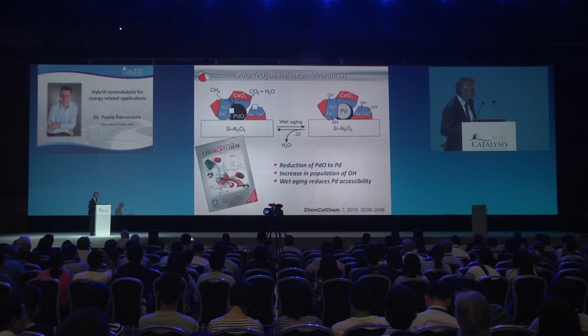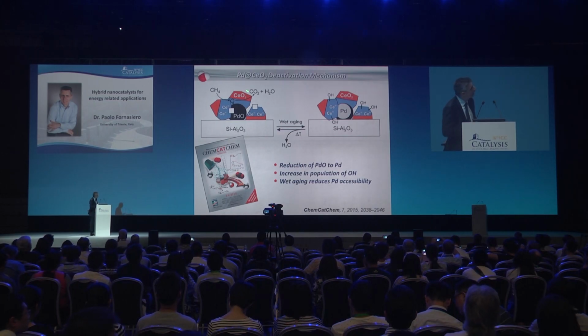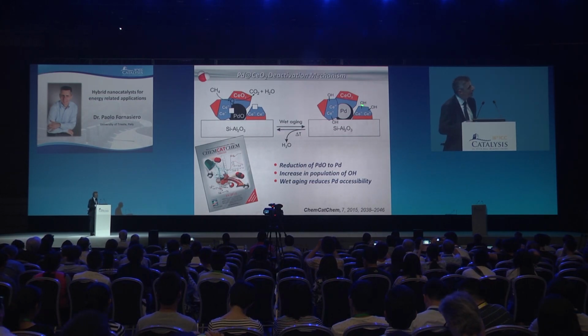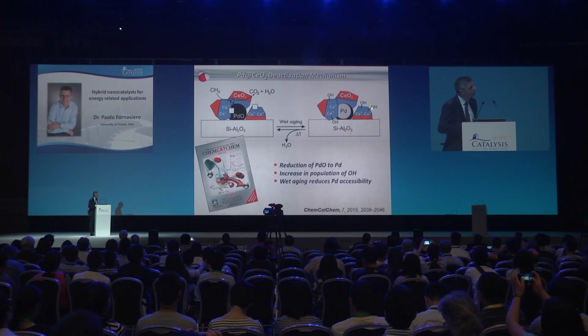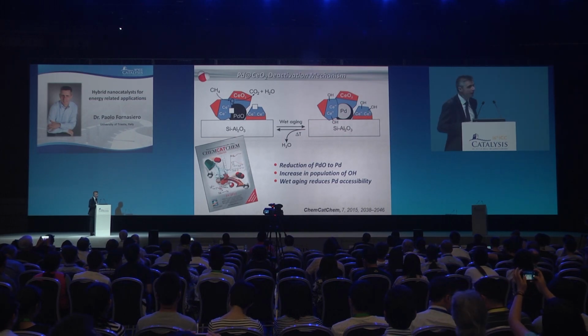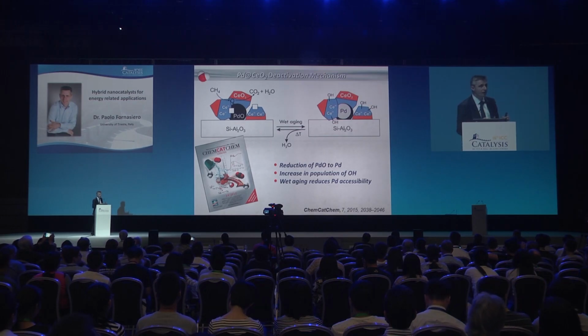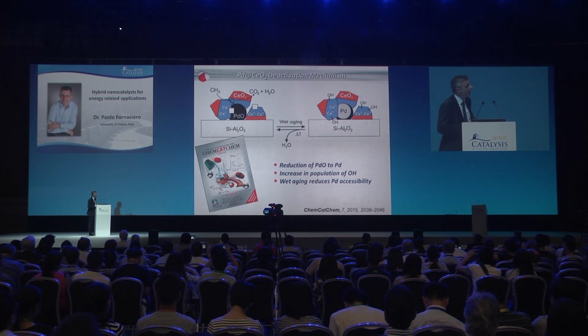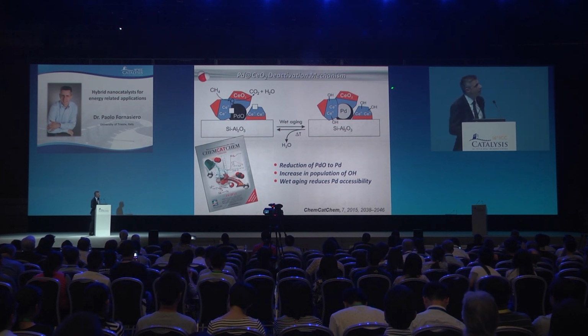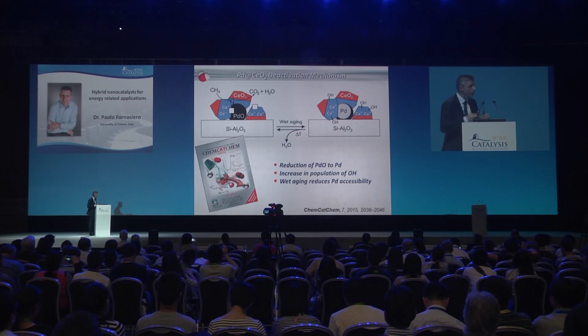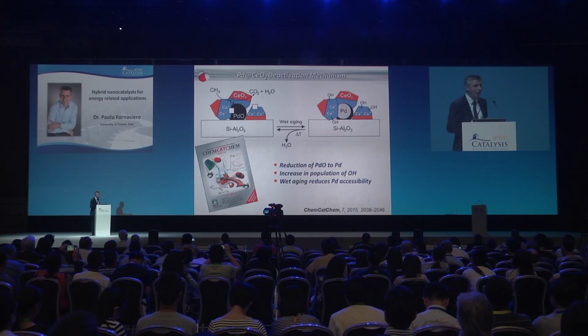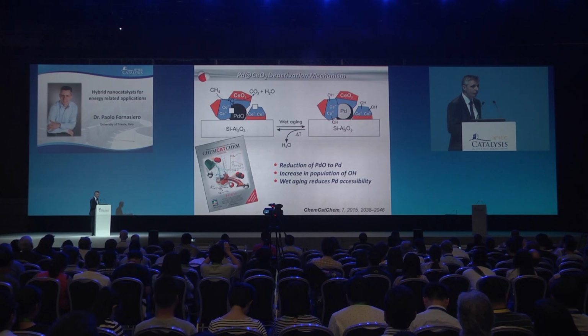So our explanation, and we got the cover of ChemCatChem, is that at high temperature in the presence of water, you form stable OH groups that block the oxygen transfer from ceria to the palladium, which then remains in the metallic state and is not back-oxidized by oxygen from the lattice, due to the core-shell structure of our catalyst. So to design something which is stable under water, we have to think about another oxide which still gives some oxygen to the palladium, but does not form these stable OH groups.